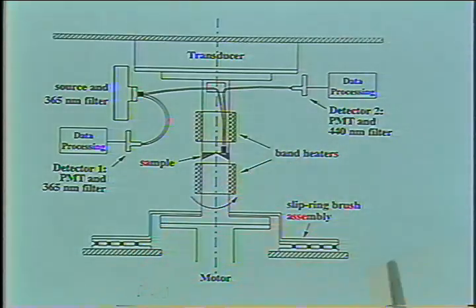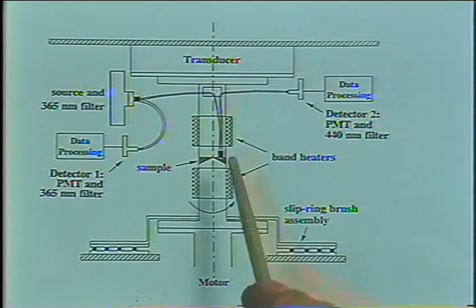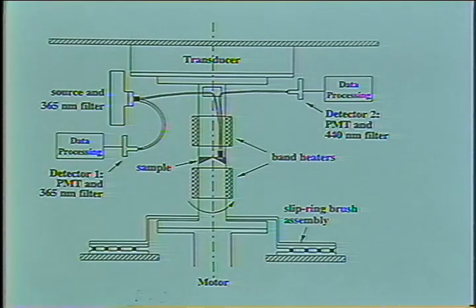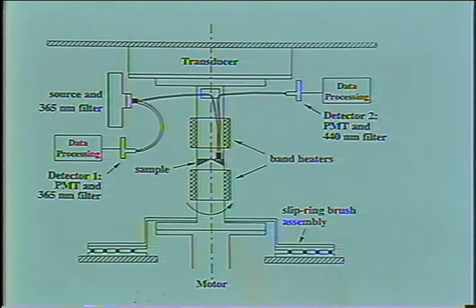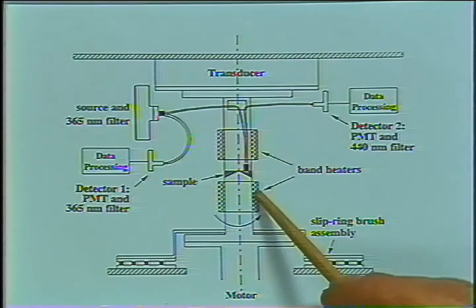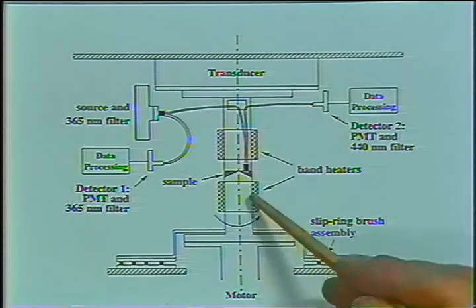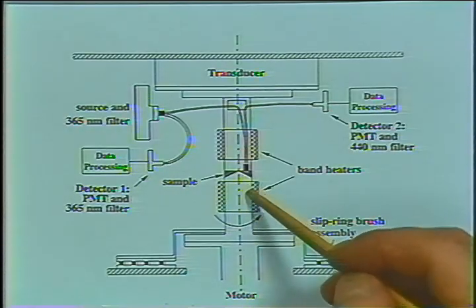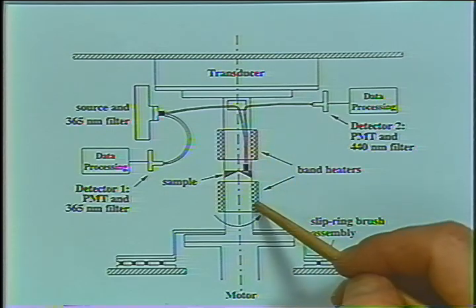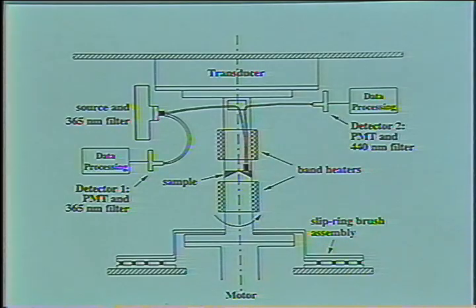But remember that we still have to supply the heat flux. So you would have a heat flux coming out from the center of the sample, center of the disk, radially outward and down the shaft. So necessarily you have a radial temperature profile produced in your rheometer when doing that. We have a different proposal for this problem, and it seems to work very nicely. We put band heaters on the shaft on both sides, and with these band heaters we produce enough energy to supply the flux down the shaft. But we also control the temperature on both sides. The temperature here and there are equal, which means that there's no flux across here, and the sample is really guarded in an area of zero temperature gradient. And this gives us the isothermal temperature conditions which we need for our experiment.